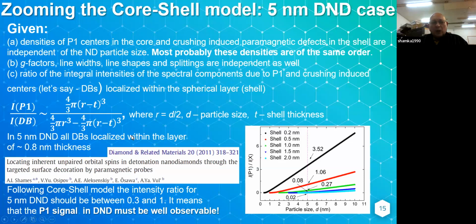Let's apply this formula to 5 nanometer nanodiamonds and dangling bonds located within a layer of 0.8 nanometer thickness, as it was found by the spin probe method and published in 2011. We found that there are two groups of spins in the 5 nanometer nanodiamond, which interact with the paramagnetic probe on the surface by dipole-dipole interaction, and it allowed us to calculate distances. And we found that the dangling bonds are located within 0.8 nanometer thickness.